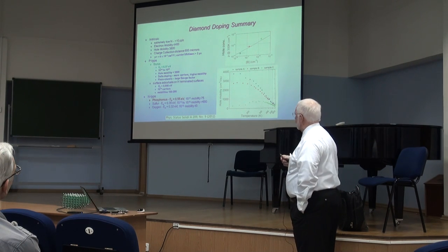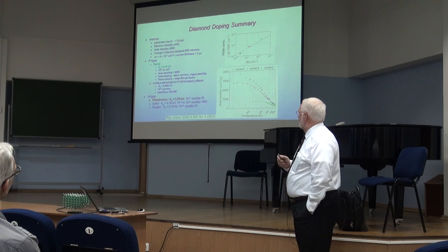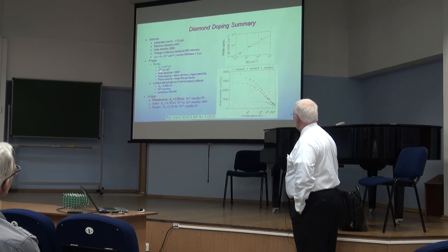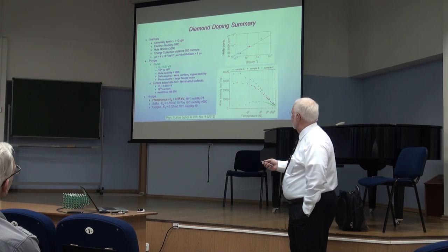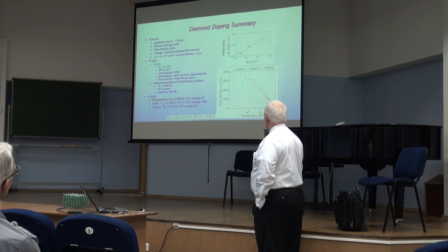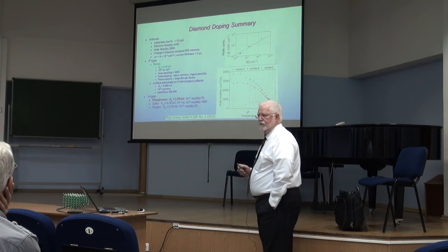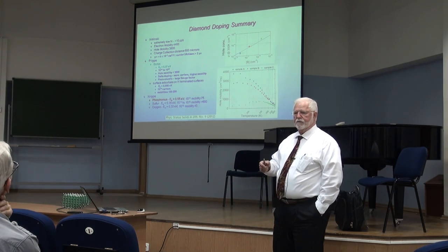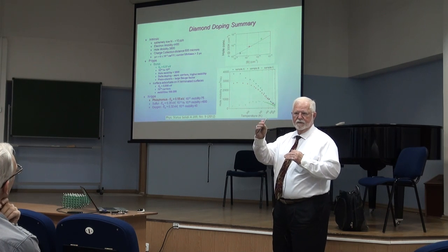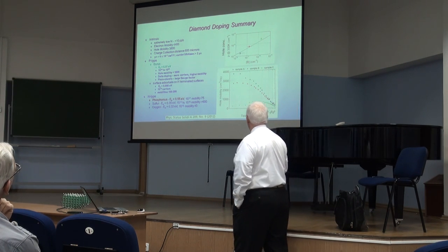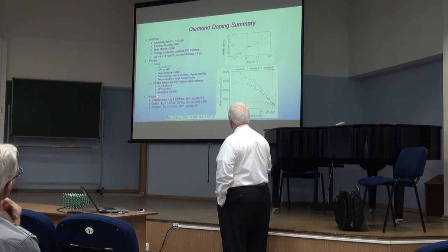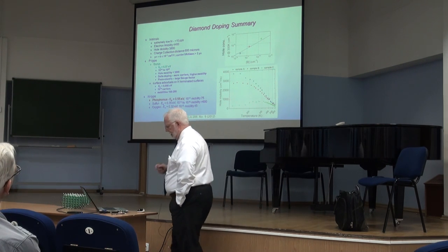So this is what really is hindering us in using diamond as a semiconductor, is that we have this deep dopant level, and if we get to high enough charge carrier concentration, we have poor mobility. Now for N-type diamond, we can do that with phosphorus, but unfortunately phosphorus has an even deeper energy level. It's about 0.6 electron volts, and so it's even worse than boron for that.